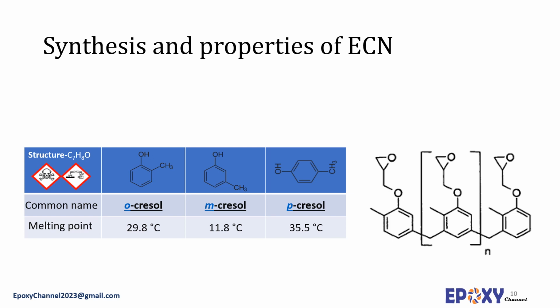Formaldehyde is used in the form of paraformaldehyde, and polycondensation of orthocresols and paraformaldehyde is carried out at 115 centigrade, first in the presence of oxalic acid until achieving 35 to 45 percent conversion, and then in the presence of toluene sulfonic acid. After the extraction of water and distillation at 65 centigrade, epichlorohydrin is added and then crushed sodium hydroxide is added. Finally, after the distillation of the excess epichlorohydrin and N-butanol, the resin is washed with chloroform and water and it is purified.